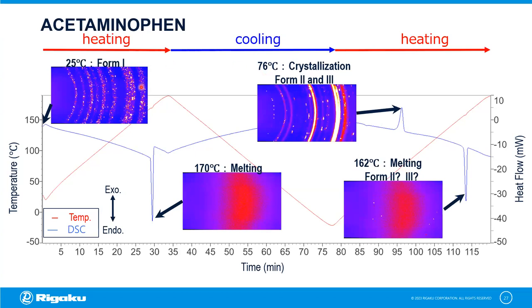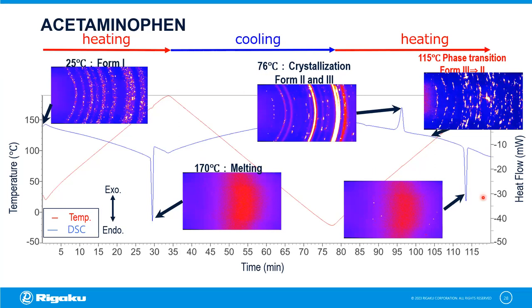So what we see in the diffraction patterns is shown here. At 25, we have form one. At 170 C, we see the melting and the formation of the amorphous pattern. We see crystallization of form two and form three at 76 degrees C. Here we see a melting at 162. Now the implication there is that we may have more than one form sitting there in the crucible. At 115 C, we also see the transition from form three back to form two. And as I mentioned, the melting at 162.